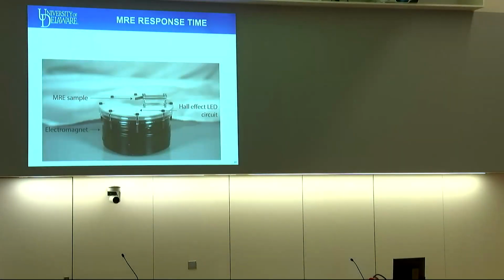In addition, these materials also can be used for direct actuation. So this video shows applying a magnetic field to a plug of the magnetorheological elastomer, and you're able to see a very fast response to the resulting magnetic field. So you can make a direct magnetic actuator that responds in a fraction of a second using this magnetorheological elastomer approach. And the small light there is a Hall effect sensor that shows when the field has been turned on.